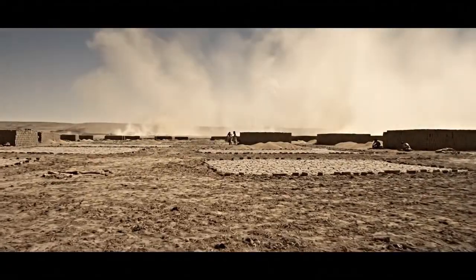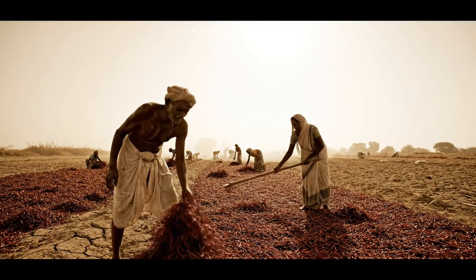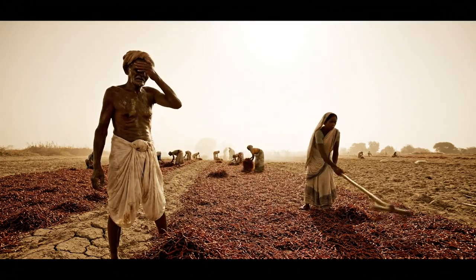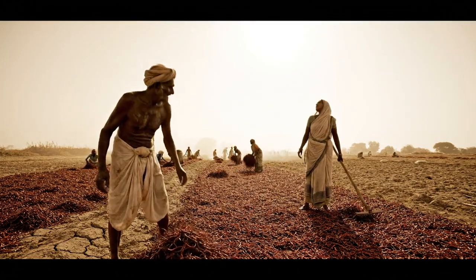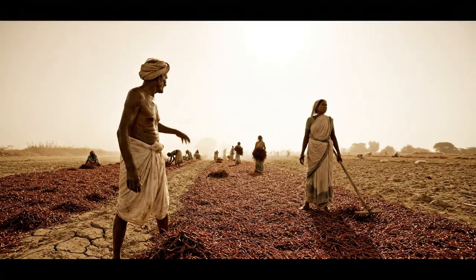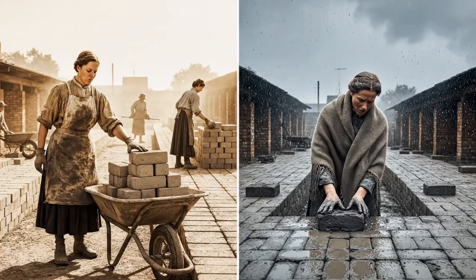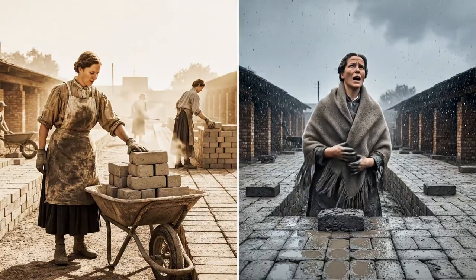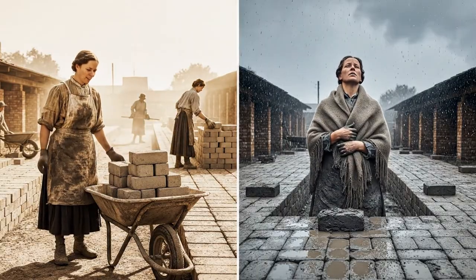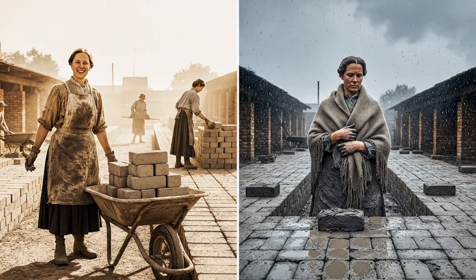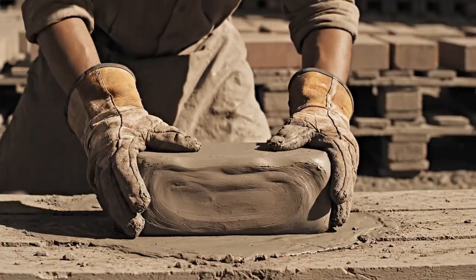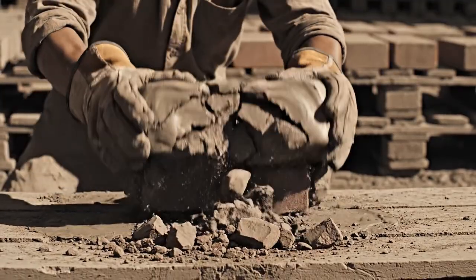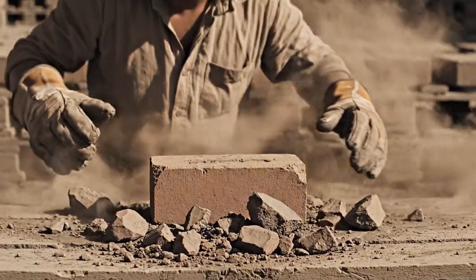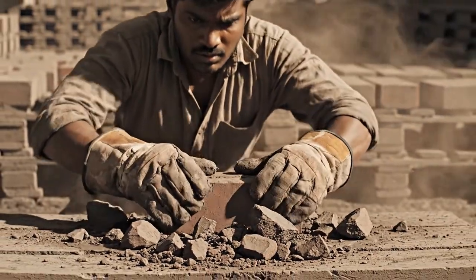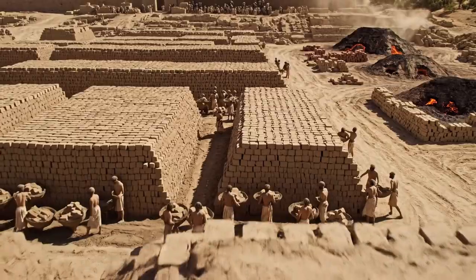Drying time depends entirely on weather. In the peak of Mesopotamian summer, when temperatures exceed 120 degrees Fahrenheit and humidity is almost zero, bricks can be fully dry in 4 days, but during cooler or more humid periods, they might need 2 weeks. And rushing this process, trying to move bricks before they're ready, destroys more bricks than any other single cause of failure in the entire operation.